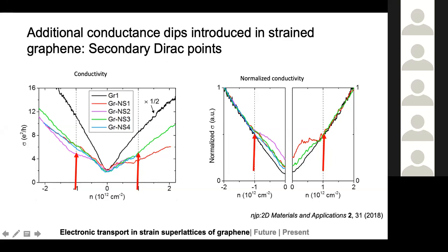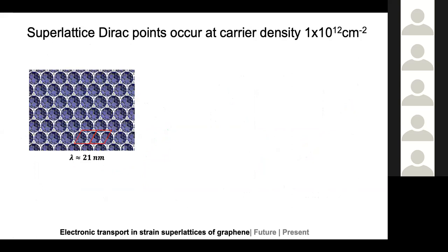So what is the origin of these kinks, which we call the secondary Dirac points? Because it seems like apart from the dip at just the Dirac point, there are these additional dips happening in the resistance, in the conductance. We can theoretically calculate the carrier density, and it turns out it matches the experimental results quite well. If you consider a bird's eye view of the superlattice, the strain superlattice will have a dimension of 21 nanometers approximately.